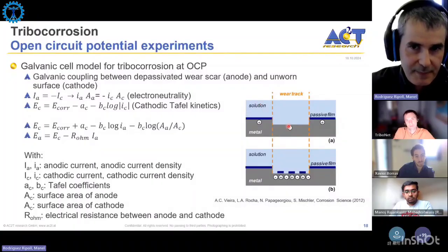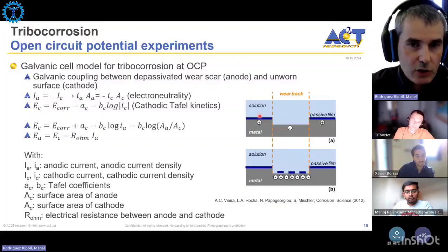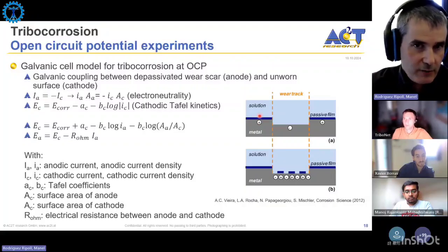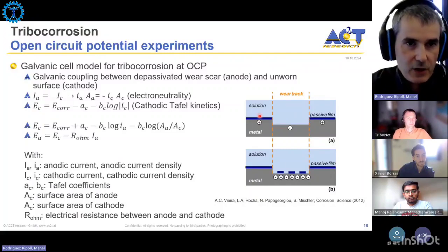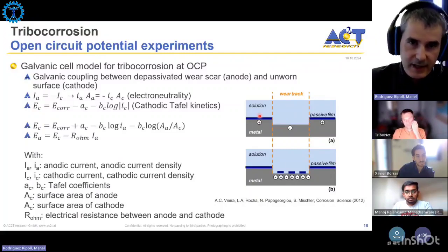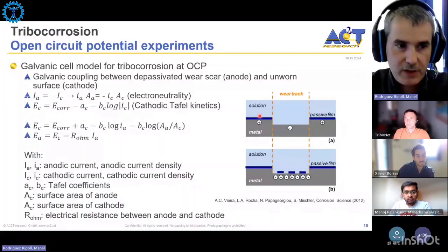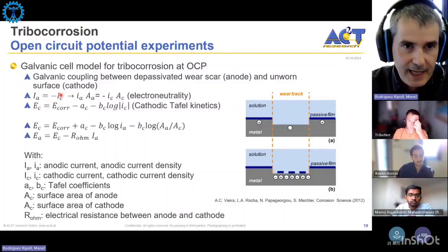So this one behaves as an anode, this one behaves as a cathode, and under OCP conditions, we don't have any current. We have seen before that it's in equilibrium. We need to have a current if we want to impose a potential. We have seen this in the polarization curves, but locally we have currents. The net current is zero, but locally we have currents that cancel each other. It means that the anodic current density is equal to the cathodic current density, and this current density is the total current normalized by the area.